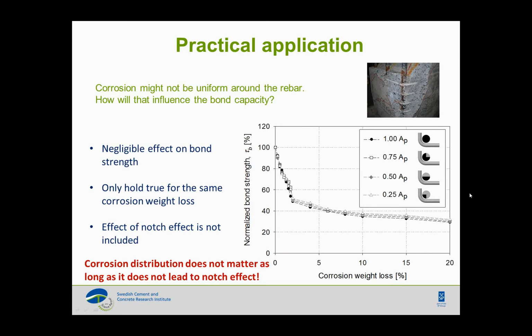as long as you stick to the same amount of corrosion weight loss, not corrosion penetration. It doesn't matter if you have it on one side of the bar, not on the other side, or not all around it. If you manage to measure the corrosion weight loss, you can actually ignore how it is distributed because it will not influence the bond strength at all in this case.